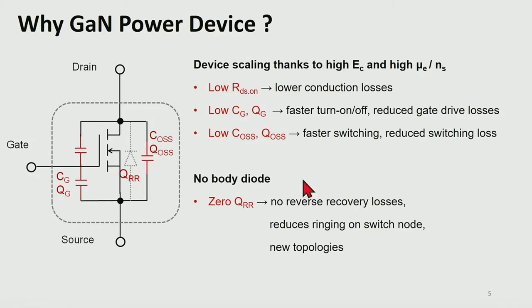To help your understanding, I put a simple circuit model for power device. So in addition to the device DC resistance, there are a couple of important AC parameters for power devices. For example, the input capacitance CG, output capacitance COSS, and also reverse recovery charge QRR. And first, thanks to the high critical electric field, GaN device can support the higher voltage with a smaller device dimension. And with a combination of a high electron mobility, the smaller device dimension reduces the on resistance, which is helpful for conduction loss reduction.